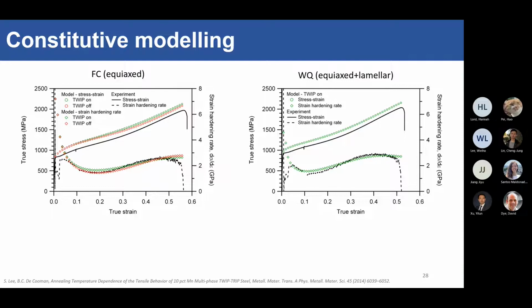So the TWIP on is the green, TWIP off is the red. And you can see in the FC steel, there is almost hardly any difference between the FC and the water quench steel. So this model here absolutely shatters 4 years of work in developing a manganese-lean TWIP steel because your TWIP does almost nothing for your steel. And I didn't even plot the TWIP off for the water quench steel because it was almost exactly the same. Your TWIP effect does very little for your steels.